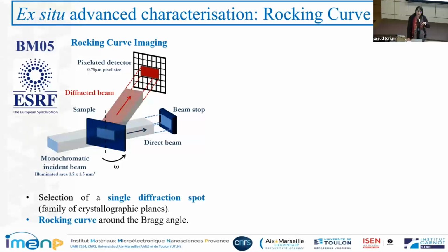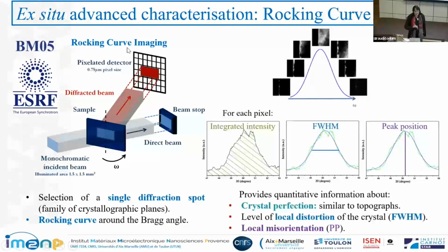This is done ex situ, so after solidification. This is rocking curve imaging. In this case, the sample is on a goniometer, and it is oriented so that we select a particular family of planes. And then a rocking curve is done around the Bragg angle, and images are recorded all along the rocking curve. And what you obtain for each pixel is this type of curves here. And the integrated intensity is very similar to what we have in topography in situ, but we can also have complementary quantitative information by fitting the curve. When we measure the full width at half maximum, it gives quantitative information about distortion, and the peak position about local misorientation.